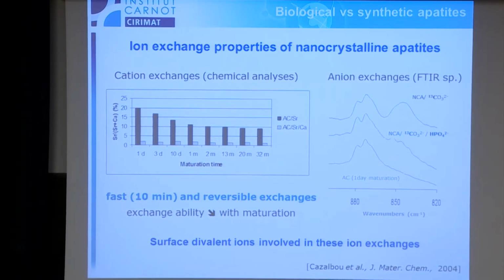We put this apatite in a solution with carbonate 13 to see the shift of the band, and you can see the carbonate 13 that has been exchanged with the apatite. Then if you put this apatite in an HPO4 solution, you can see that these bands decrease a lot, showing that most of the carbonate 13 that was first exchanged is reversibly exchanged with the HPO4.